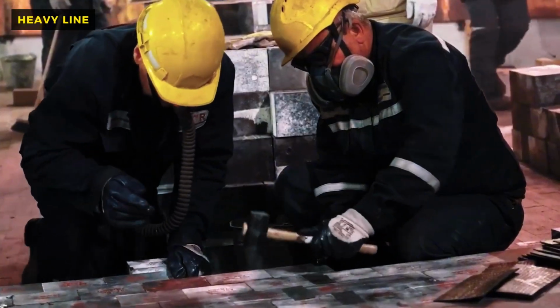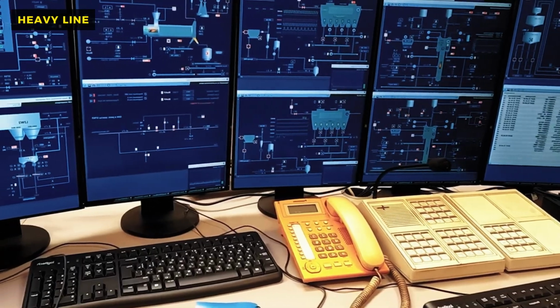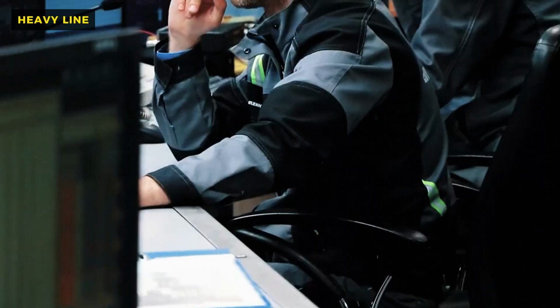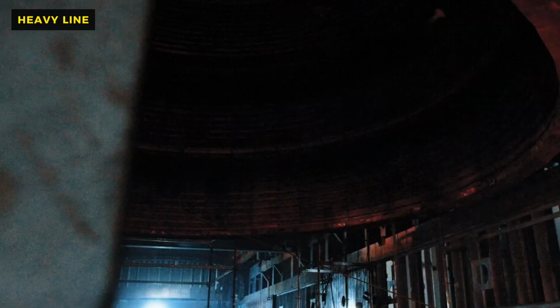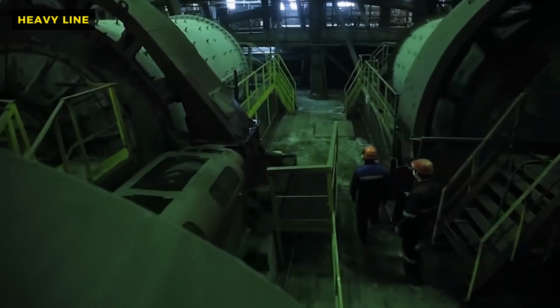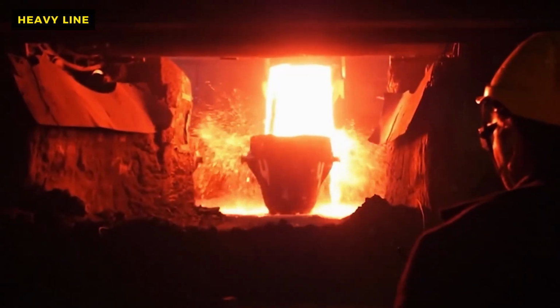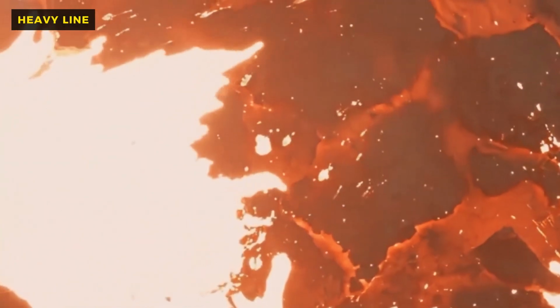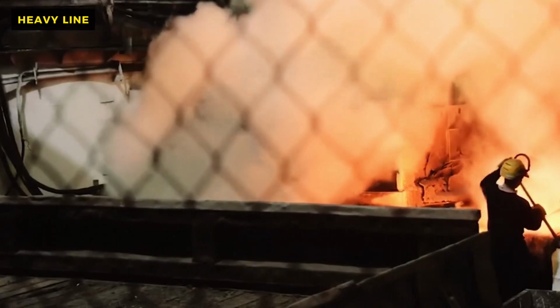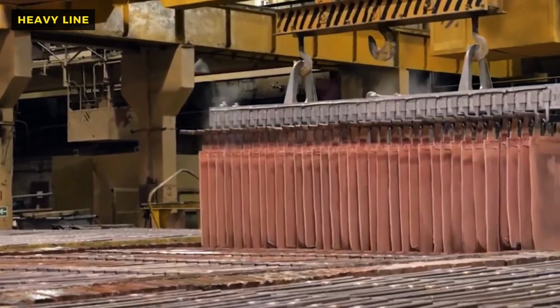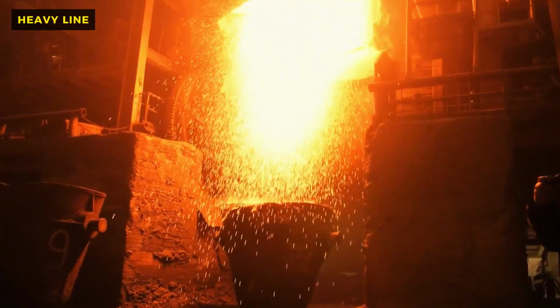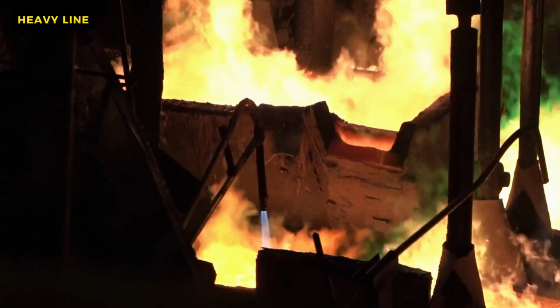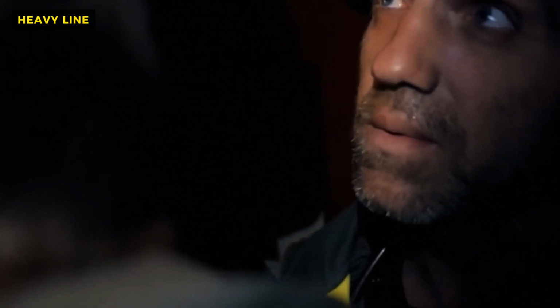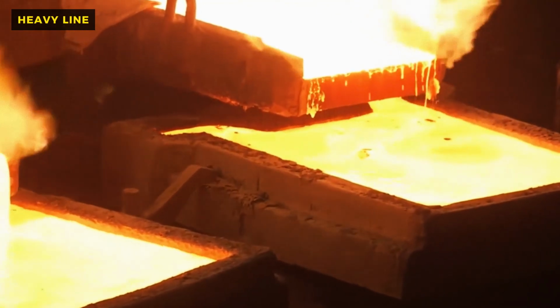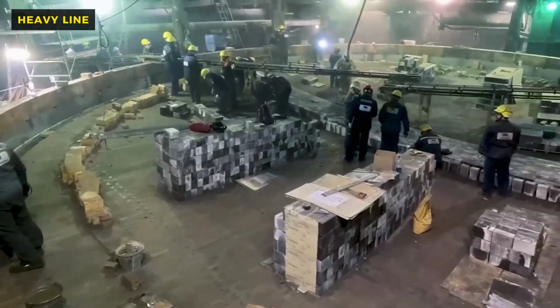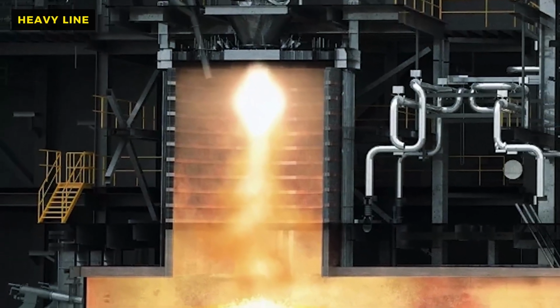The sulfur in the ore reacts with the oxygen, burning with a ferocious intensity that drives the temperature inside the shaft to over 1,300 degrees Celsius. The particles of metal melt in midair, raining down into the settler hearth below, like a storm of liquid fire. In the hearth, gravity takes over. The heavier mat, containing the valuable nickel and copper, sinks to the bottom, while the lighter slag, composed mostly of iron and silica, floats on top.